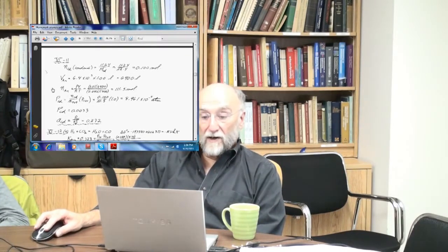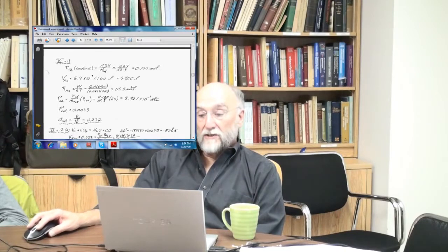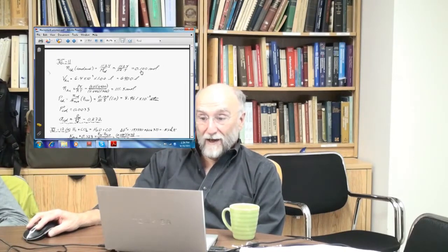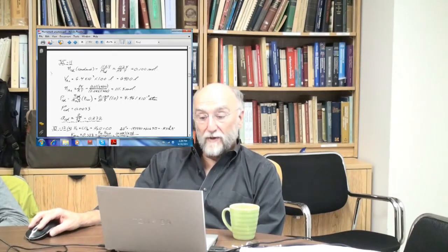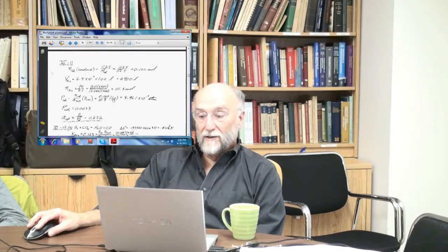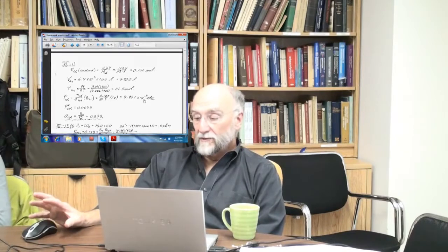Okay, so the number of moles of argon was PV over RT. So you had 111.5 moles of argon, which contained 0.1 moles of cadmium, assumed to be at equilibrium with the liquid. So the partial pressure of cadmium is the mole fraction of cadmium in the gas times the total pressure, by Dalton's law. Okay, so the partial pressure of cadmium is this, under the assumption that the gas was saturated with the cadmium. The partial pressure of pure cadmium is given, but you could measure that. You could just repeat the experiment with pure cadmium and measure the partial pressure of pure cadmium. So the activity of cadmium is 0.272.